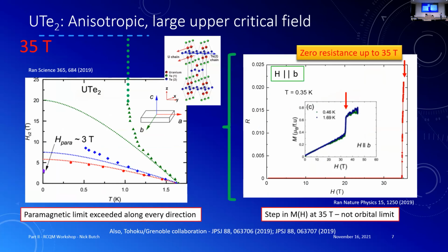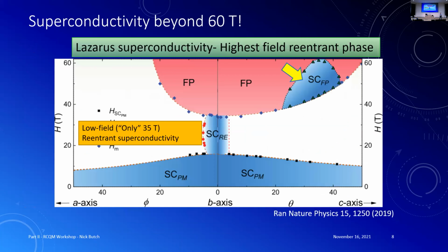Okay, it is characterized by this. So if you measure the magnetization, there's a jump. It's still paramagnetic. There are features in the resistivity that are associated with that. It extends out to fairly high temperatures, at least 20 Kelvin, then it kind of goes away. Is it saturated? No, it keeps going. It's not a very large number, right? And I'll show you some data from other groups later. But yeah, so there's a change in the magnetic ground state. Let's at least say that. And this thing lives on the high field side of it, okay?